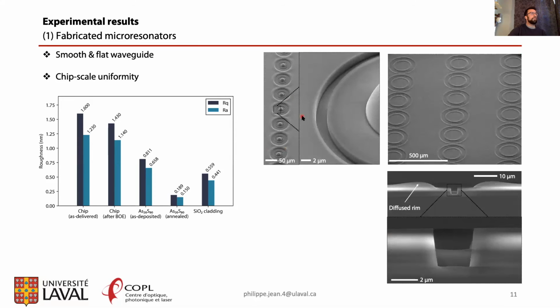Okay, here you can see the fabricated microresonators, and you can see SEM images on the right of a few different microresonators. You can see the waveguide that is relatively flat and smooth inside the trench, and you can see that there's a pretty good uniformity that was observed over the chip scale. And here you can see a cross section of the fabricated waveguide with the diffused rim. We mentioned maybe that the diffused rim is really regarded as sacrificial material, as we're only interested in the material that actually ends up in the microtrench and really forms a waveguide.